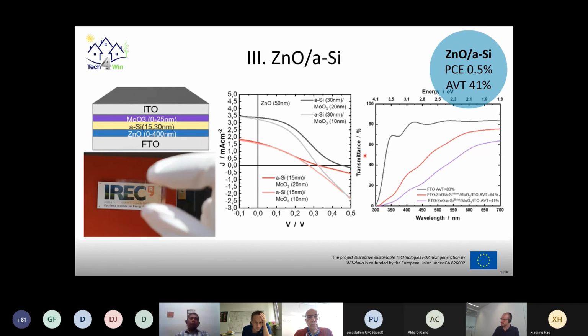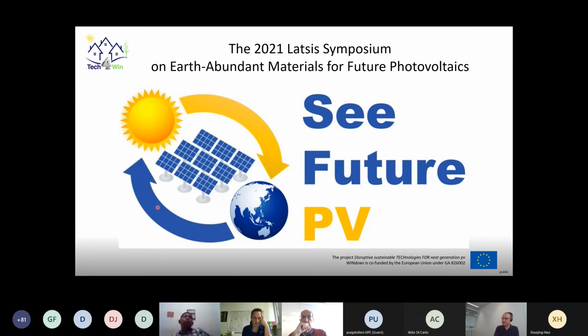Because indeed, if you look at the transmittance again, where we put again the FTO as a reference, you see two cells, one cell with 15 nanometer of amorphous silicon in red, so the higher transmittance, and one cell with 30 nanometers of amorphous silicon in pinkish magenta, I guess, which is a bit lower transparency, which is indeed 41%. The other one is above 60%, is 64% for the AVT. And even for the thicker one, it looks quite well visually, as you can see here again, on an IREC logo, where you see it's very well transparent. This will be presented in November, beginning of November, at the Future PV conference in EPFL in Switzerland. And in the meanwhile, of course, we will try to publish as well.